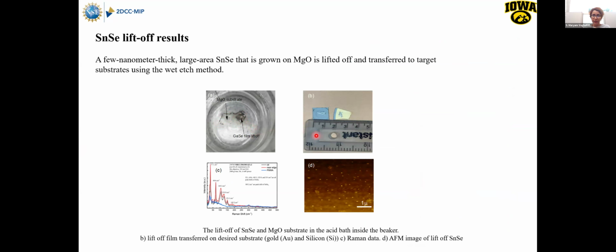And then we could transfer it to a different substrate like gold and silicon. This is just a sample. We can transfer to any substrate we would like to. Raman also confirmed our data. At that time, because I had limitations going through the fab facilities, you can also see some peaks from the PMMA here because I needed to clean up with the acetone and ethanol. However, we can see the Raman spectra for the tin selenide. So it's confirmed that we have the tin selenide here, and the AFM data show the film.